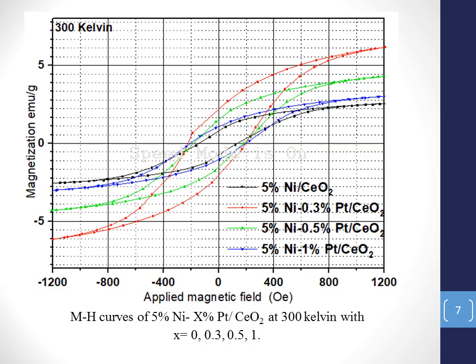The magnetic measurements of samples recorded at 300 Kelvin show a ferromagnetic behavior for all the samples. According to previous reports, stoichiometric CeO2 is diamagnetic. The ferromagnetic behavior is related to the exchange interactions between unpaired spins resulting from surface oxygen vacancies of CeO2 and dopant ions. So substitution with metal ions should create more oxygen vacancies and enhance the ferromagnetism.